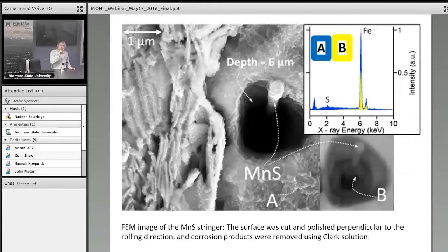So this is a 1 kV image. You don't see anything. What is beneath here? Here is something sticking out, and this is a manganese sulfide stringer. And then you change it to 20 kV, use backscatter, and now you can see inside of it. So this is the same hole, but taken at a different keV. So remember this trick.